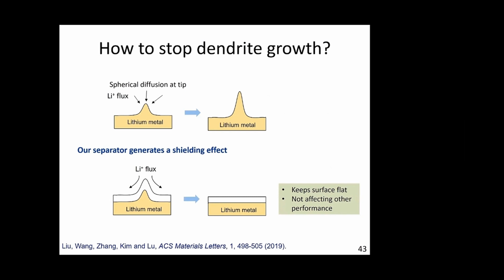How to stop dendrite growth? Lithium deposition is inherently unstable because of unavoidable perturbation. See, a small protrusion is formed here. The lithium flux forms a spherical diffusion concentrated toward the tip. Therefore, the tip grows faster and forms a sharp dendrite. This dendrite easily penetrates the separator, called short circuit.